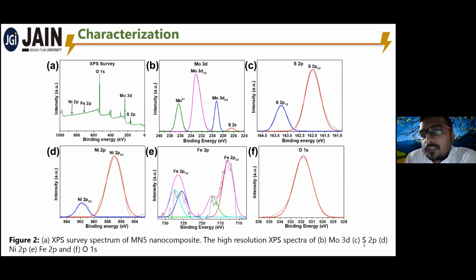In the sulfur spectrum, we can see that there are two peaks, S 2p1/2 and S 2p3/2, which show the sulfur is in the S2- state. That means these two clearly show that the MoS2 structure is present in the nanocomposite.